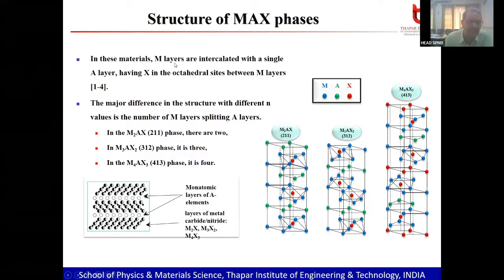In these materials, M layers are intercalated with a single A layer having X in the octahedral sites between the M layers. Okay. The major difference in the structure with different n values is written over here. You can see M2AX, 211, because of the M2. In M3AX2, because it is M3, so it is 3, A is 1, X is 2, the 312 phase. And M4AX3, this is the classification and categorization of the material. Because M is 4 over here, so we put 4, A is 1, X is 3, the 413 phases. So like that, we are going to categorize these materials.